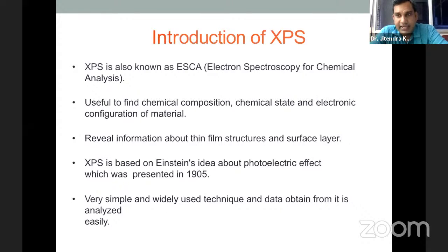Because in EDS, we always select the element. If you know the element, then only you can select it manually, and then it gives you some percentage, weight percentage or atomic percentage, whatever. But if you don't know any composition in your compound, you get some material and you want to know what the composition of this material is, then go for the XPS. So this XPS analysis is used to find the chemical composition and chemical state.